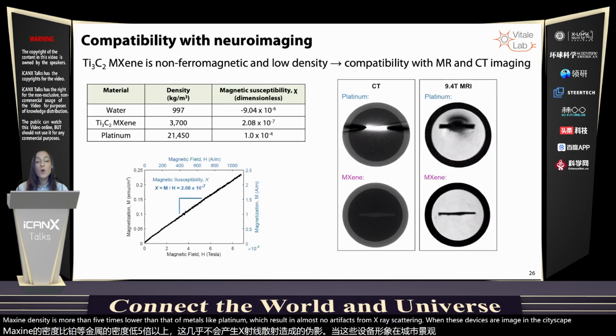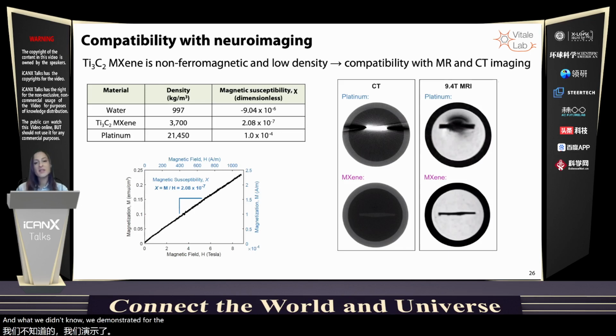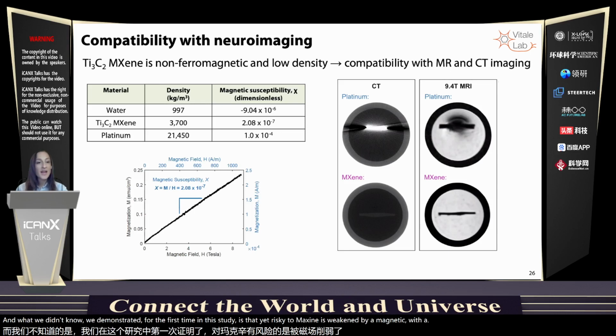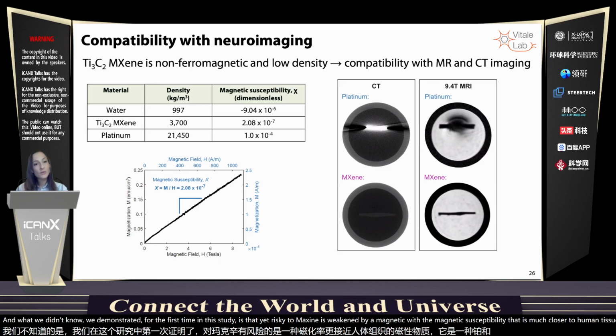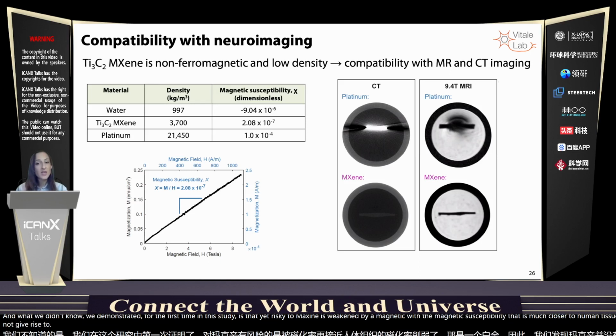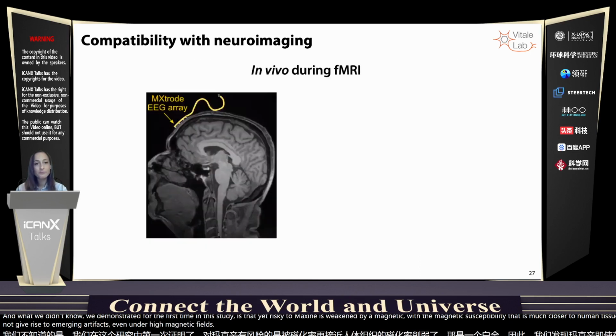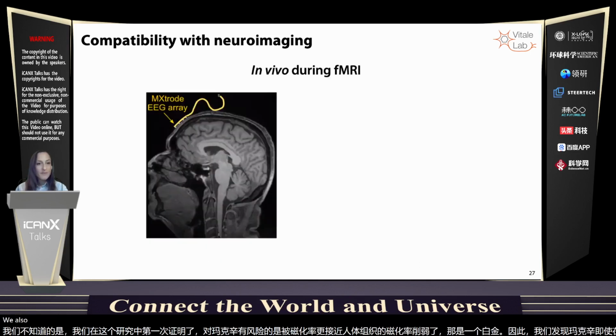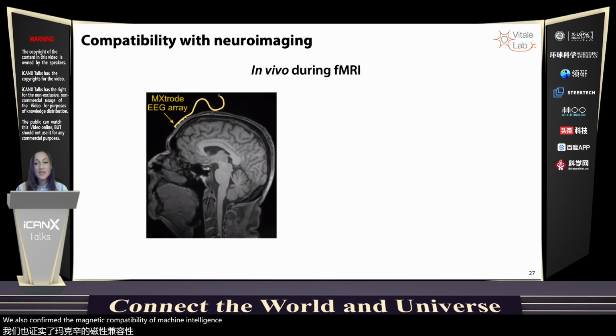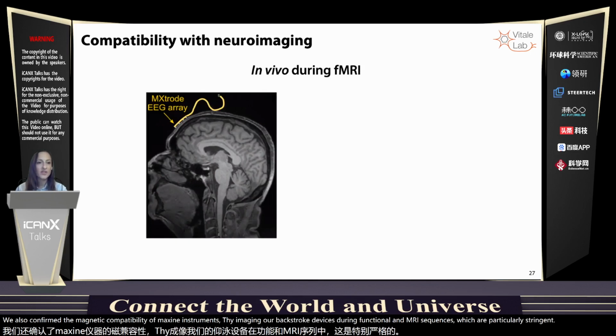And what we didn't know, and we demonstrated for the first time in this study, is that Ti3C2 MXene is weakly paramagnetic with a magnetic susceptibility that is much closer to human tissues than that of platinum. And as a result, we found that MXene does not give rise to imaging artifacts even under high magnetic fields. We also confirmed the magnetic compatibility of MXene in humans by imaging our MXtrode devices during functional MRI sequences, which have particularly stringent artifact requirements.